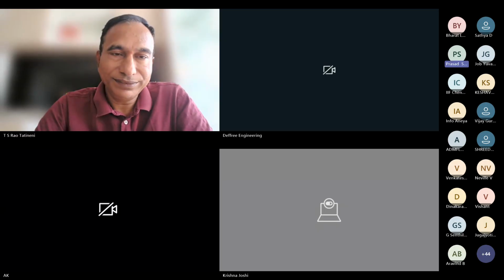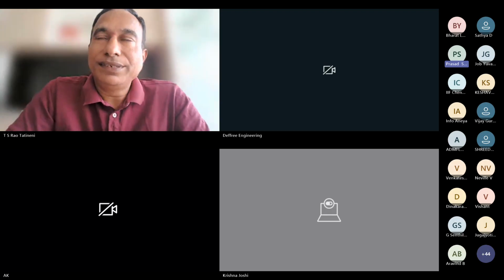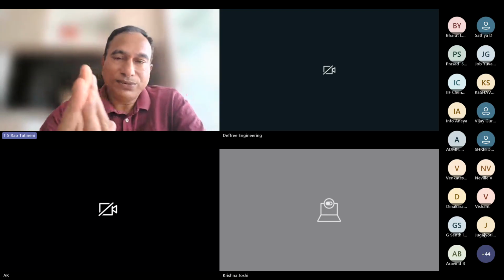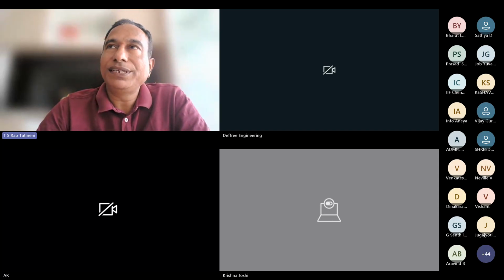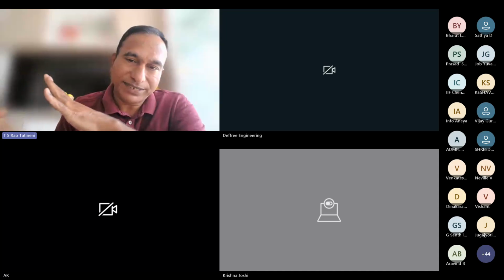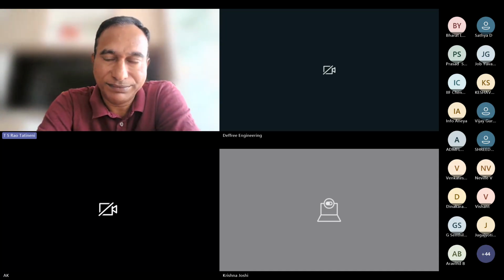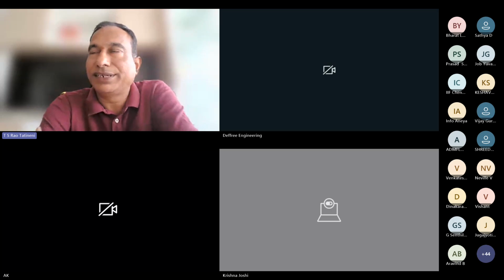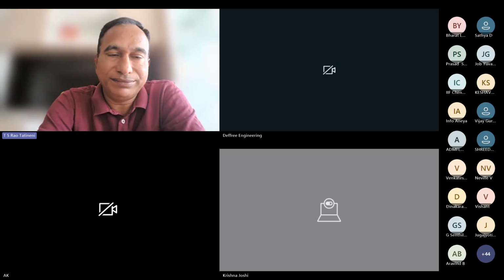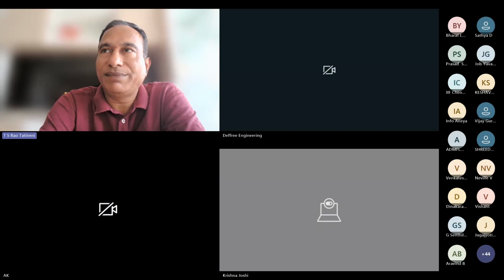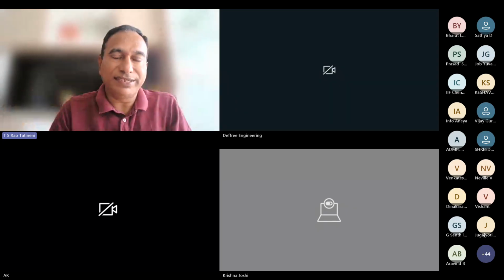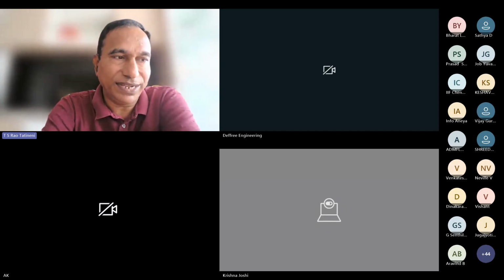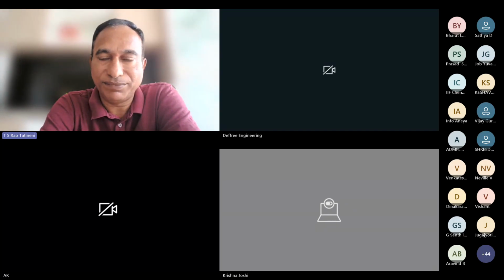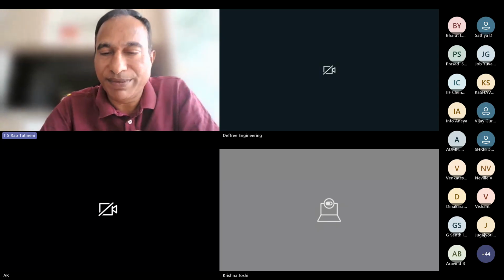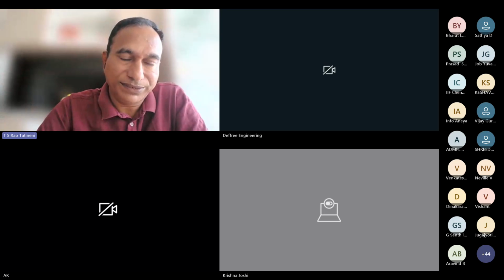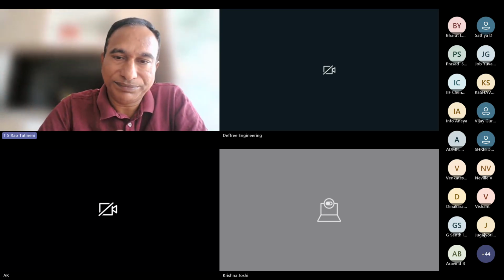What is the percentage of slag that may go inside, as per your practical experience? See, if it is liquid slag, it is very difficult to prevent with the filter. About 50% of the liquid slag may get entrapped in the filter, but the balance 50% is likely to float along with the liquid metal. So it is always recommended to prevent generating liquid slag. One of the parameters is the temperature. If the temperature is very high, the liner is likely to get melted and gets into the liquid slag. There are many parameters that affect the liquid slag. Very difficult. Only 50% we can prevent through the gating, but the balance 50% we need to stop at the origination of the process.